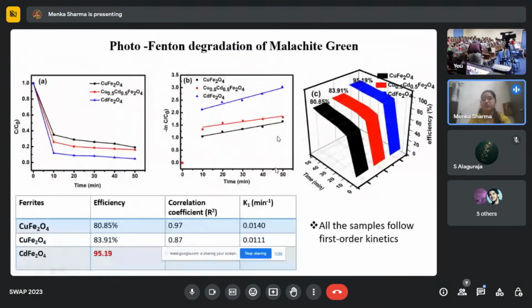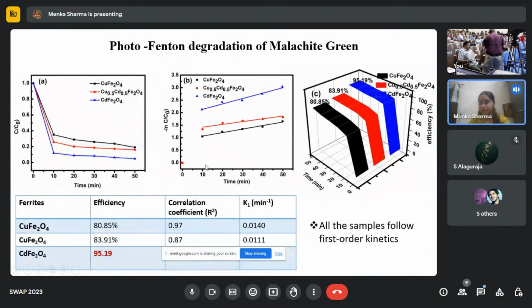The next pollutant is malachite green. We observe the same result. The degradation efficiency is maximum in the case of cadmium ferrite, and all three samples follow first order rate kinetics. So the same phenomenon, physisorption, is happening here. Because of physisorption, we can say that there is a weak van der Waals force acting between the photocatalyst and the pollutant.